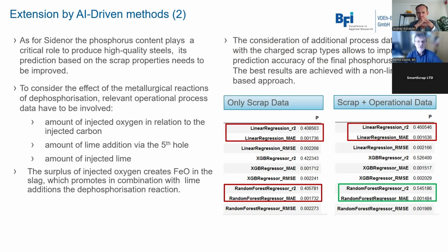So we simply said that we have to consider that the phosphorus content not only depends on the contributions of the different scrap types, but also on the amount of injected oxygen in relation to the injected carbon, the amount of lime addition via the fifth hole, and also, in case it is performed, the amount of injected lime. So we know that the surplus of injected oxygen creates iron oxide in the slag, which promotes, in combination with the lime additions, the dephosphorisation reaction.